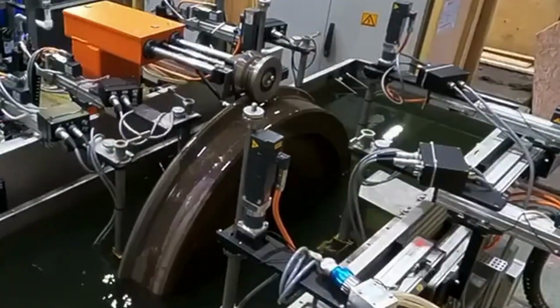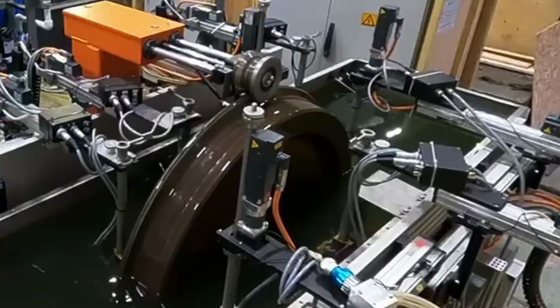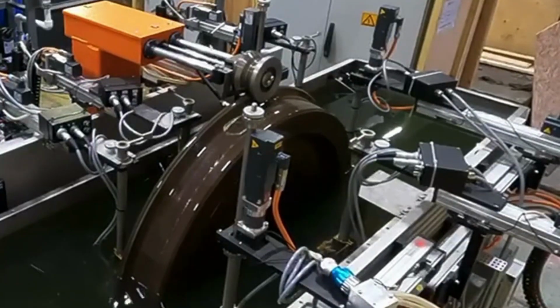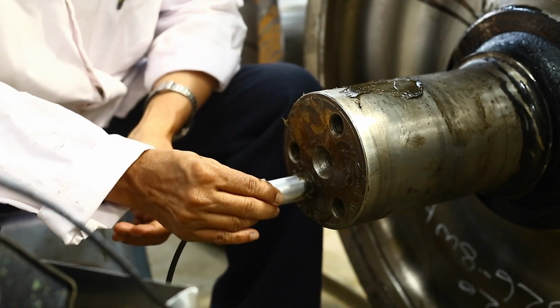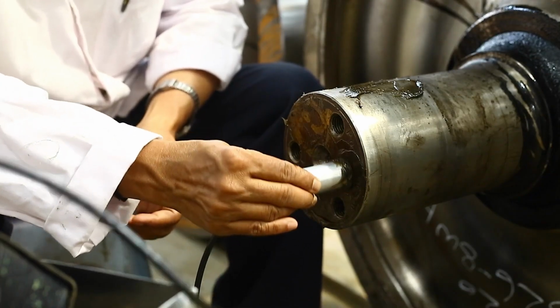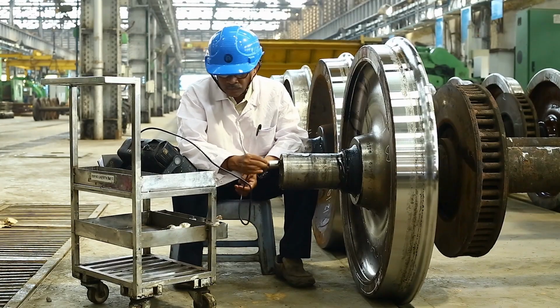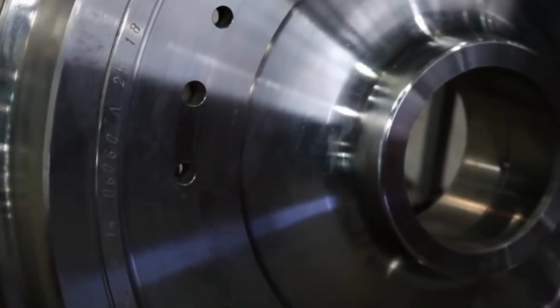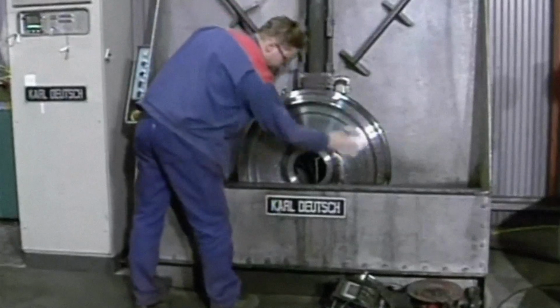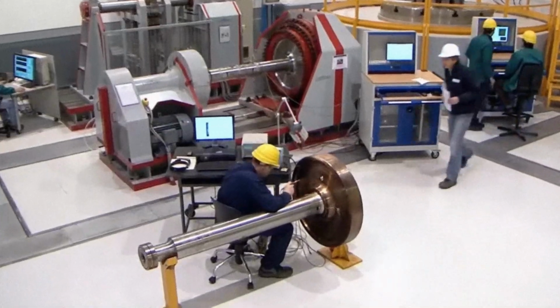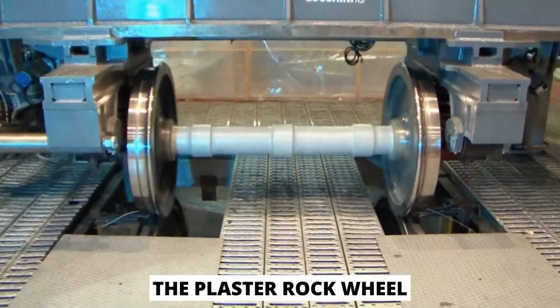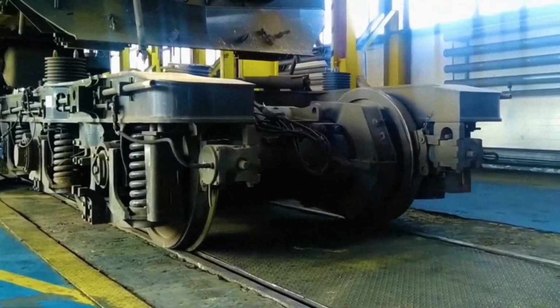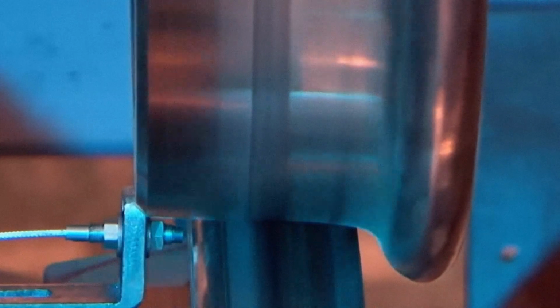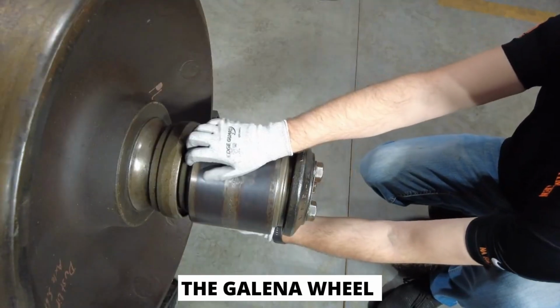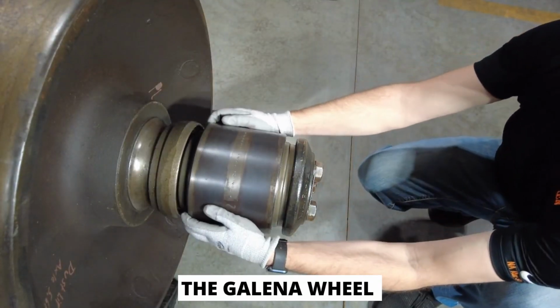The limitation is geometry. Ultrasonic testing works best when the sound wave strikes the defect at a perpendicular angle. A crack oriented at an unfavorable angle relative to the transducer may not produce a clear reflection. A crack that has grown into a complex shape, branching, turning, may produce ambiguous echoes. The Plaster rock wheel passed 2 ultrasonic inspections over 23 years. The Galena wheel generated 4 near-threshold wild readings before it failed.